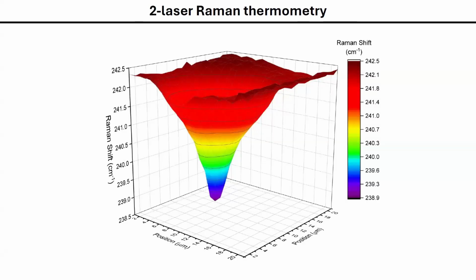Thank you very much for this question, because I didn't even have the chance to show it in my thesis. We did perform 2 laser Raman thermometry. We used the second laser to heat up our materials, and we performed maps of how this Raman shift changes with temperature. You can retrieve the entire temperature profile in your films, which would potentially contain more information about heat transport in these materials.